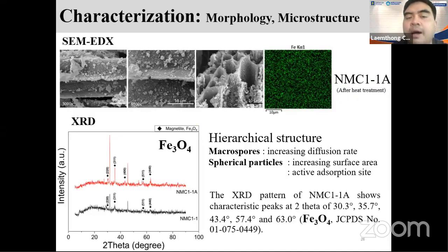And then it recombines by condensation and makes particles, if you can observe here. But the iron particles are trapped inside these particles. I will show you later from the TEM image. And we checked by XRD and we see that, by using a simple method, we can get the structure of the magnetite. So that means we have good magnetic properties of this kind of material.